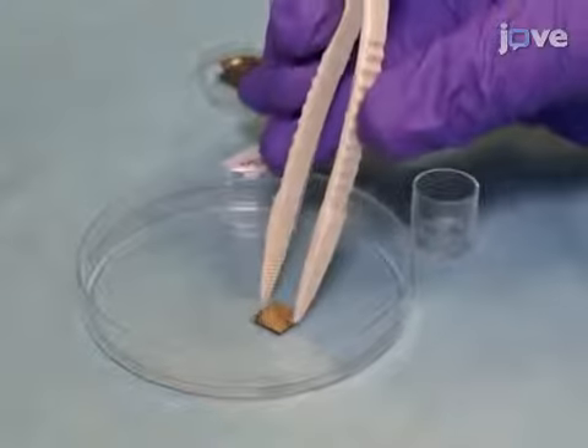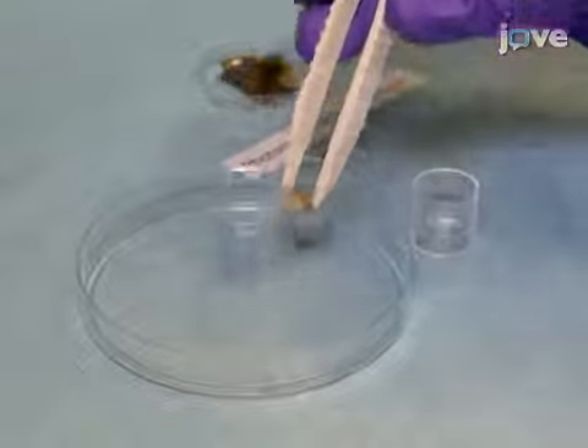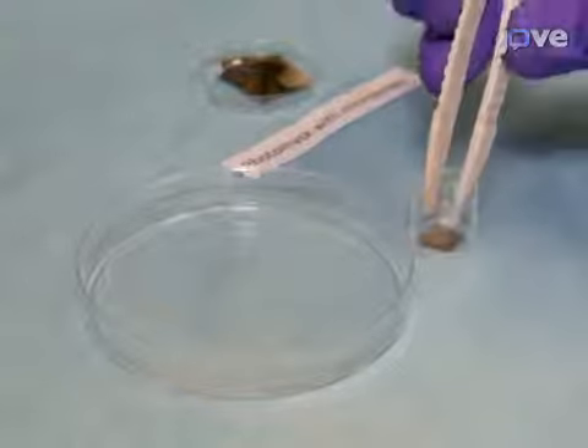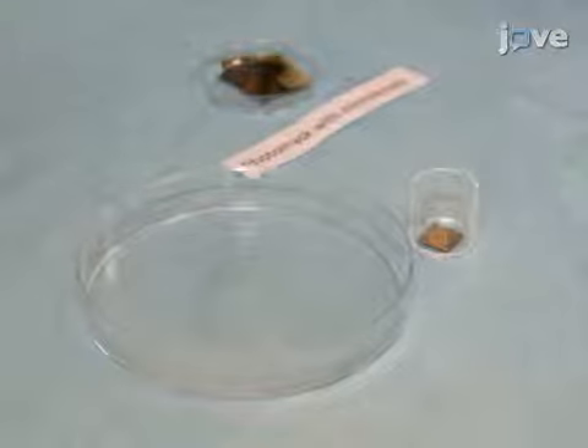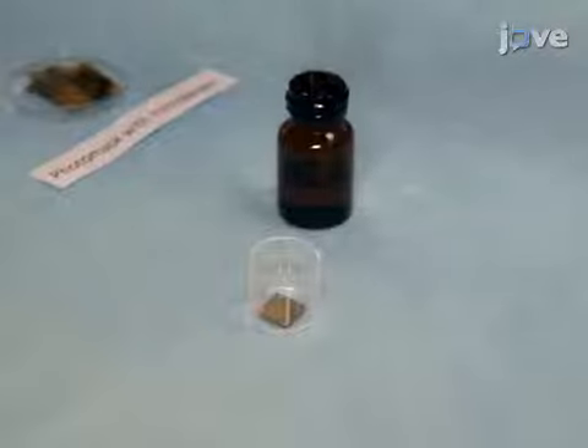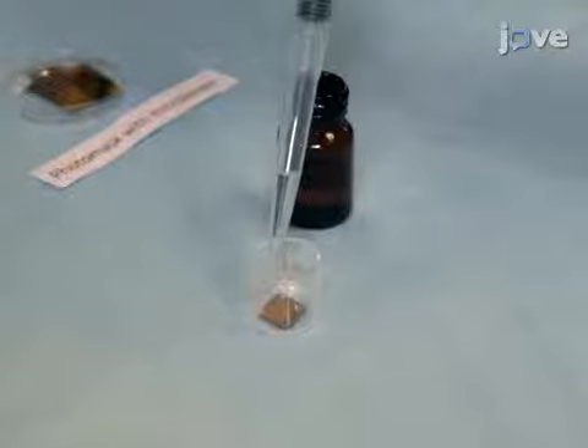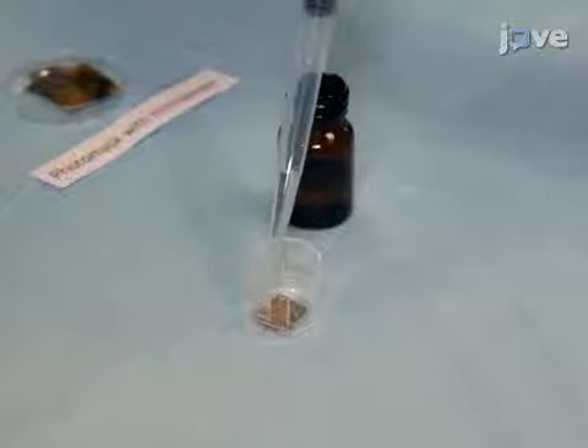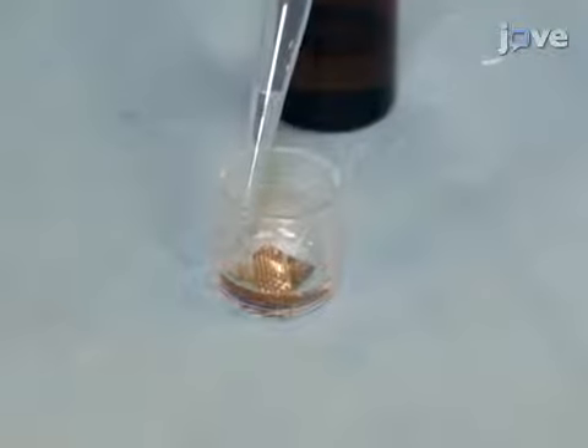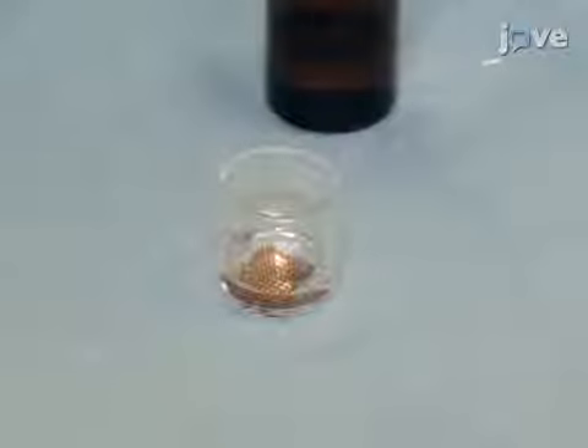With forceps, place the microneedles attached to the photomask into a well of a 24-well plate, needle side up. Add 300 to 400 microliters of the prepolymer solution into the well until the needles are submerged to the height of the desired backing layer.